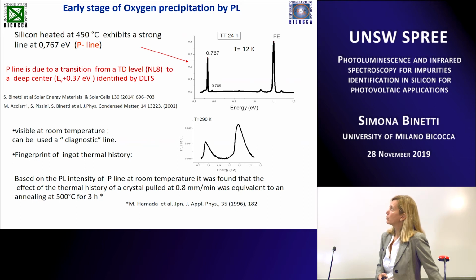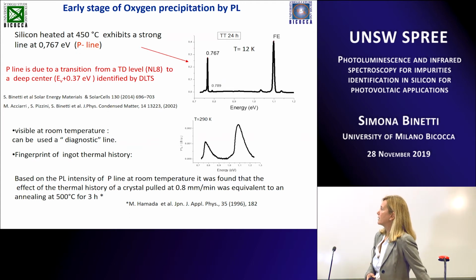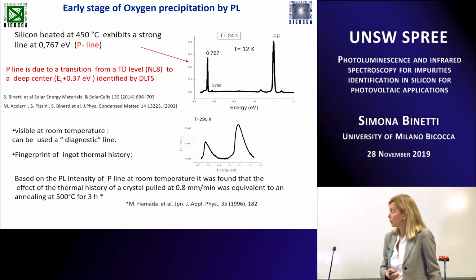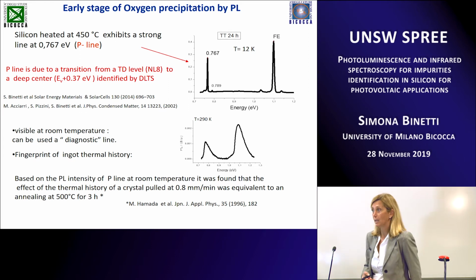The P line is curious because sometimes it is also present at room temperature, so you can detect the P line at room temperature. And in some peculiar work of some years ago, these Japanese researchers used the presence of this visible room temperature line as a diagnostic line to follow the thermal history of the ingot. Based on the intensity of this line, they found that the effect of the thermal history of their crystal puller was equivalent to an annealing at 500 degrees C for 3 hours. So, considering that 500 is quite a dangerous temperature for the formation of thermal donors, most probably in any Czochralski ingot that you also use for PV application, you can have some thermal donors inside.